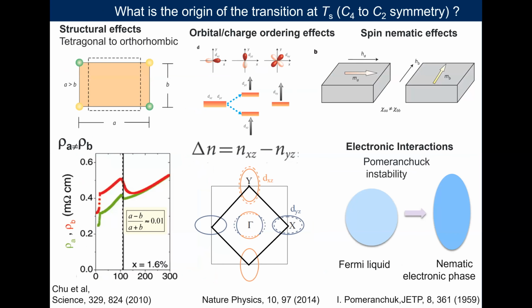Now, when we think about the nematic phase, which occurs at a particular transition, we have to consider the different types of scenarios which could give rise to those phases. First of all, we have a symmetry breaking, so the symmetry changes from C4 to C2 as the system goes through a transition, which also has structural changes from tetragonal to orthorhombic. At the same time, because we have the dxz and dyz orbitals degenerate in the tetragonal phase, we expect that the lifting of that degeneracy is the trigger to cause orbital and charge ordering type effects, and gives rise to changes in the population of the bands with xz and yz character, leading to their distortion in different ways depending on their orbital character.